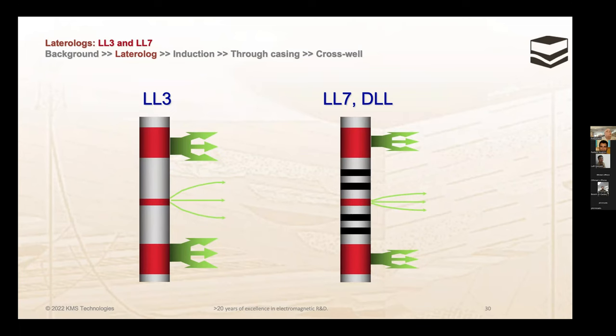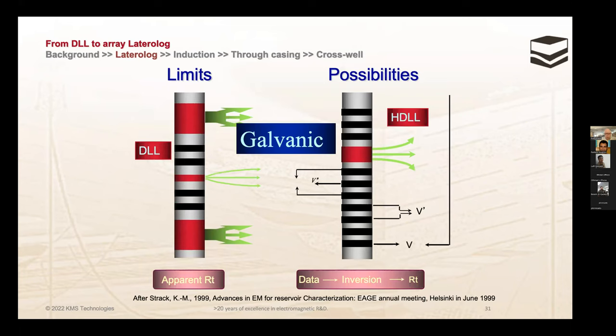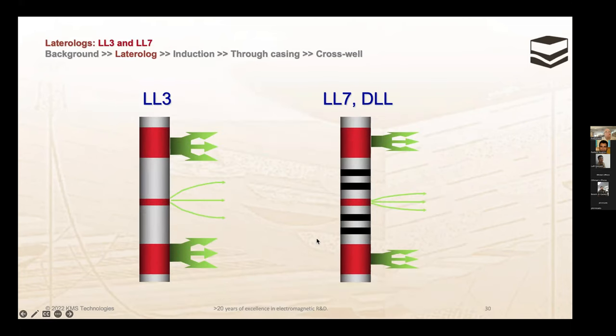And so in the LL7, which came later, and in the dual lateral log, you inject the current and you have two voltage measurement electrodes. You measure voltage here and there, and you inject as much current that the voltage here is zero. That means you're squeezing this current into a very thin layer and you get finer layering in the formation. And then you measure the current you have injected in the center electrode and the voltage at this electrode. And from there, you know the resistance at that particular layer. Remember, it's an apparent resistivity, but the logging company calls that resistance. That's incorrect, but it still works very good.